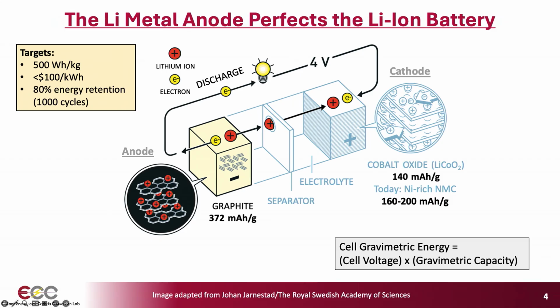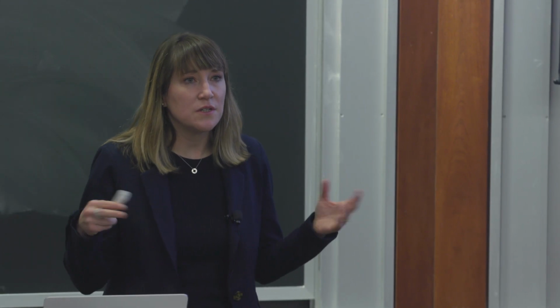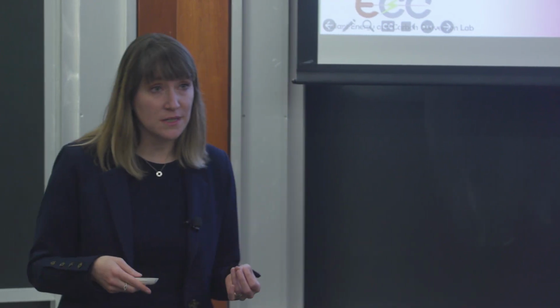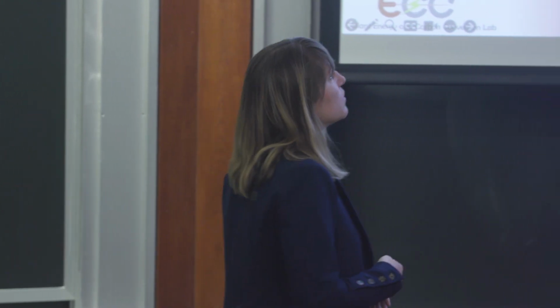The cell energy density is the product of the potential difference between the two electrodes, or the cell voltage, times the amount of charge we can store, or the gravimetric capacity. Both of these are sensitively determined by the selection of the electrode material. The improvements that I mentioned before in energy density have largely been due to improvements in the cathode design, moving from lithium cobalt oxide in initial commercialized cells in the 1990s to today's higher capacity materials like nickel-rich NMC, with relatively limited innovation on the anode side.